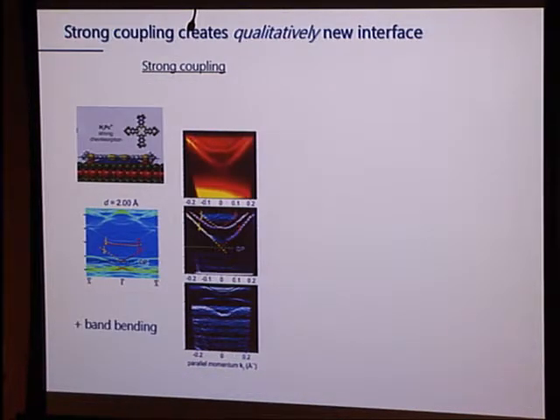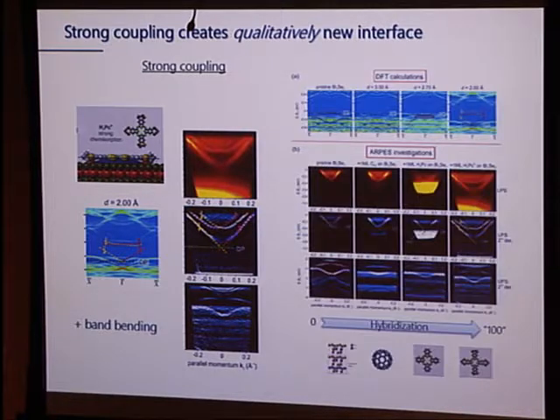Now, let's go further and let's modify that molecule. And we just modified it by adding some groups on the outside. And we put it on there. And this is what you get. Now, I would submit that this looks qualitatively different from anything that I've shown you so far. Right, let's just put them all back together. Pristine bismuth diselenide through some weak interaction, through some hybrid interface state, to this. Something very different happened here.